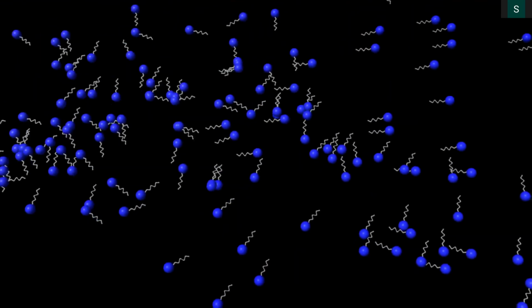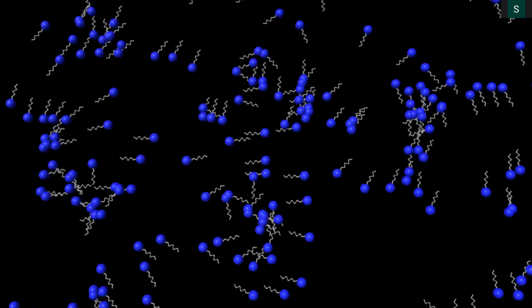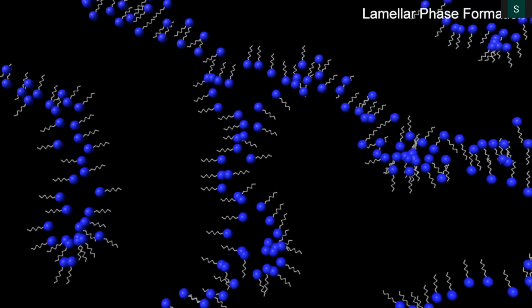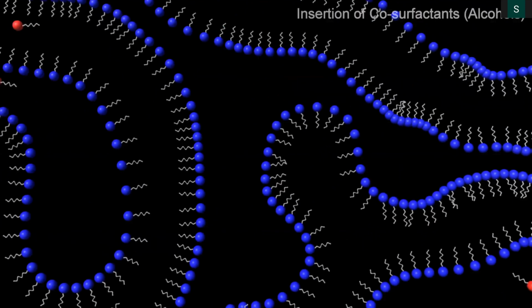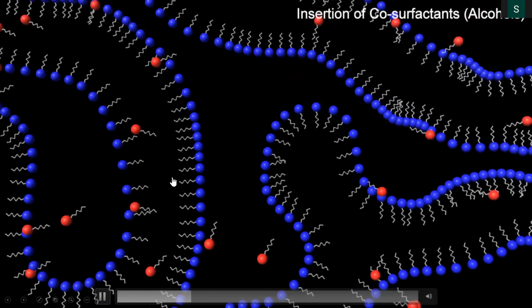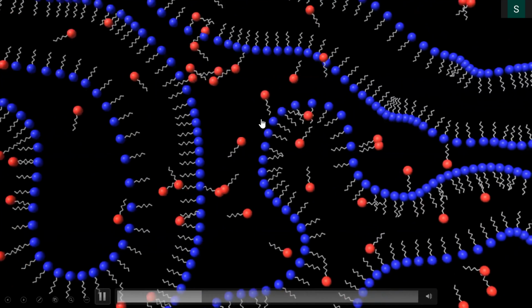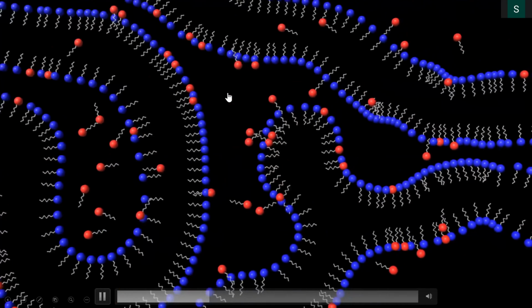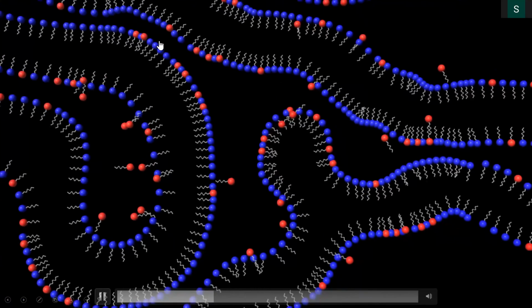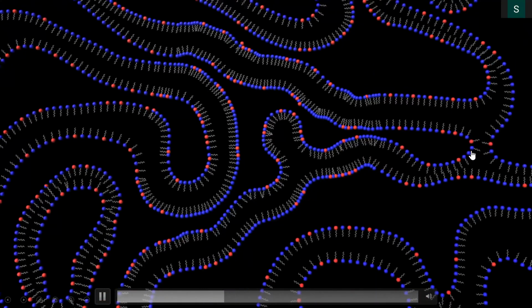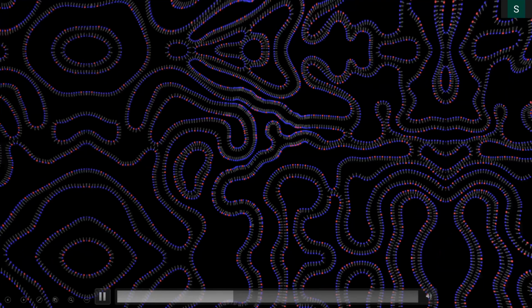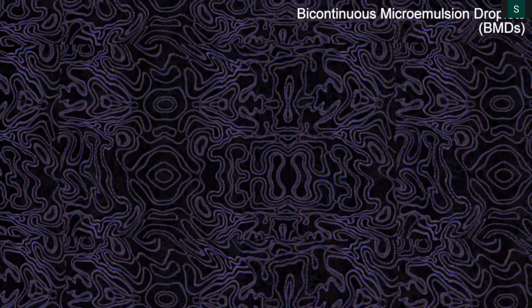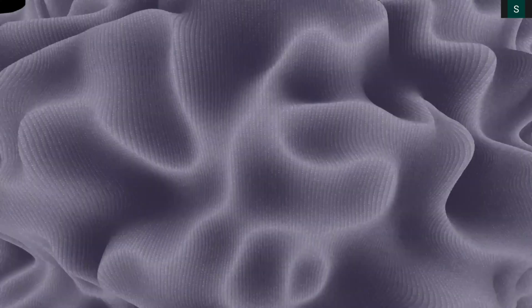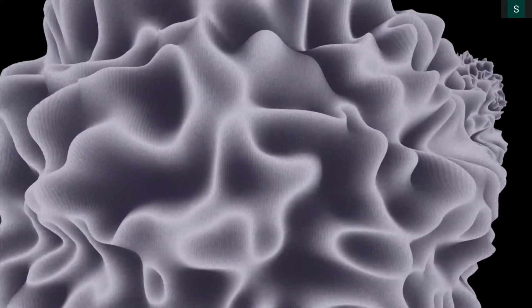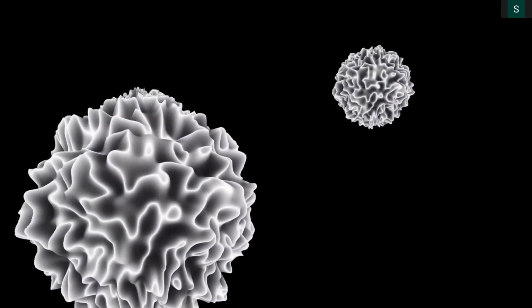to minimize the total energy of the system, because there's lots of repulsion if they are randomly oriented. So they try to self-assemble and orient properly so that they will have a minimum repulsion. They form these lamellar phases, but there are still a repulsion between this quaternary nitrogen. So we added one more co-surfactant, pentanol, having this OH polar group, and they stabilize these interfaces. What we observe is these lamellar phases are not flat floating in the solvent, but they are in the form of a droplet. They're in the form of a microemulsion droplets. And these droplets are the reactor. These droplets are the template made up of just water, xylene, and the CTAB.